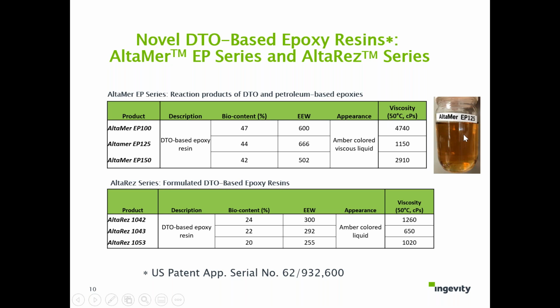This is a picture showing what the EP epoxy looks like. And then we made this AltaRez series epoxy. It's called formulated DTO epoxy, starting with an EP material and another epoxy like EPON 828, and we make these 3 AltaRez reagents. It's ready to use. So you can use this material for your applications. The bio content is from 20% to 24%, EEW from 250 to 300, and the viscosity at 50C is from 650 centipoise to over 1,000. And this is the basic DTO epoxy reagent properties.